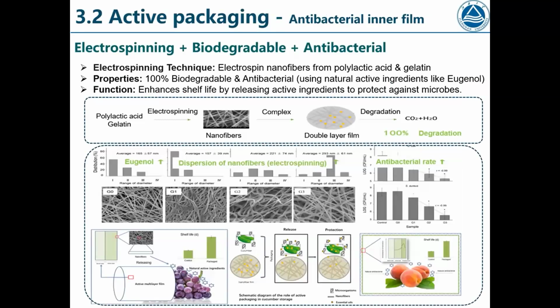Next is our work on active packaging, where the package itself plays a role in preservation. A double-layer film was made by electrospinning technique to create a nanofiber layer with polylactic acid and gelatin as the outer layer, and the inner layer was infused with natural antibacterial agents like eugenol, derived from cloves, a kind of flower. The films are fully biodegradable. During packaging, this film could slowly release the active ingredients and create a protective gas environment.